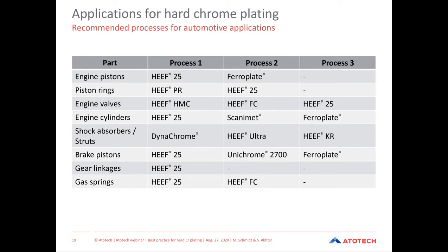If it's about automotive, the processes used in automotive industry or also in general for functional chrome plating, there is no standard process for each and every application. There's always options depending on customer requirements and plating technology used, which kind of process is used. You see here a various palette of different processes for the certain parts which are plated. As an example, for shock absorber rods, in the middle of the table, you can use a high-speed system like Dynachrome with specialized chemistry for that application. But it's also possible to plate them in a traditional way in conventional lines, where you would choose a HEEF type of process to plate these kind of parts.